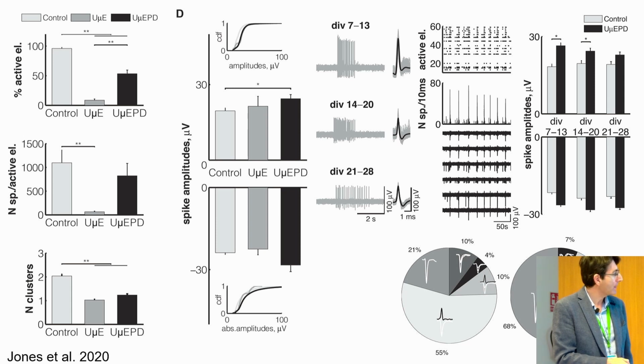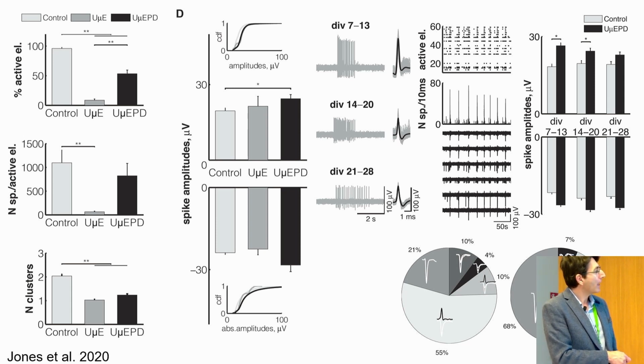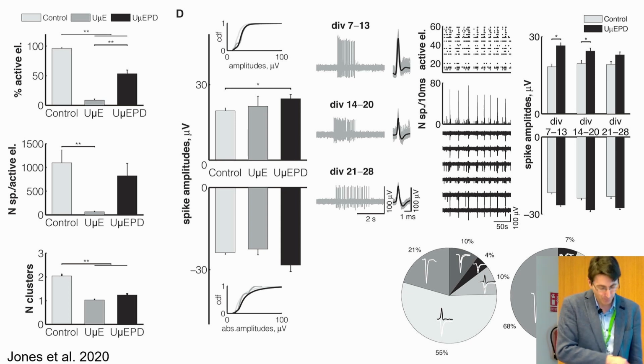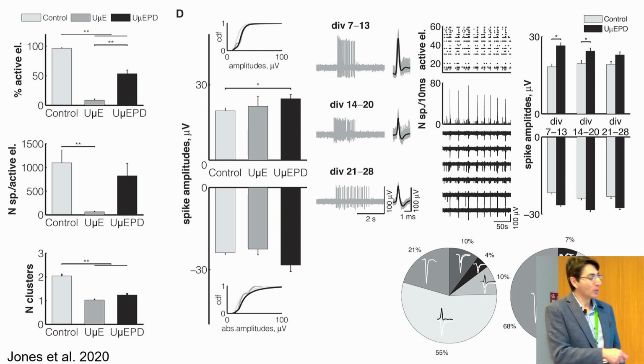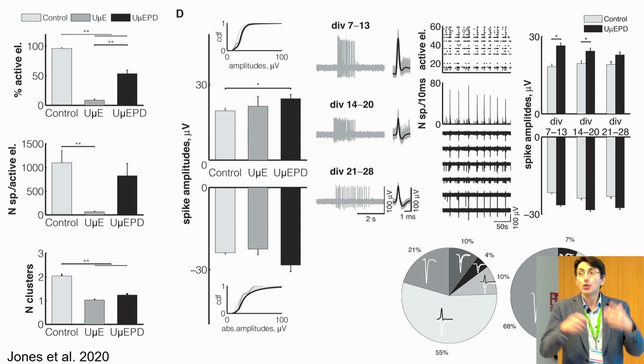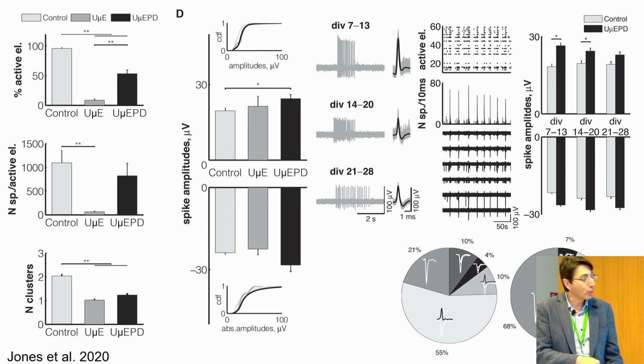What was, however, very interesting is that just for free, while there was no change or very little change in the comparison between the control and these ultra-micro protruding electrodes in terms of how many electrodes are active, how many spikes per electrode are detected, in this graph for the control condition, one electrode, like one microphone, is able to record several shapes, several units, and so it requires so-called spike sorting to make sense and potentially to separate the sources. But with the protruding electrodes, and it could be maybe obvious, could be trivial because they are so small, a large majority were only recording from a single unit.